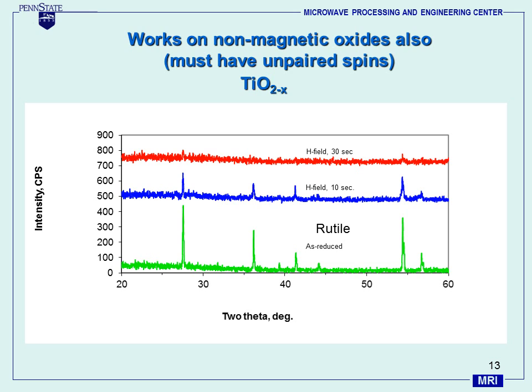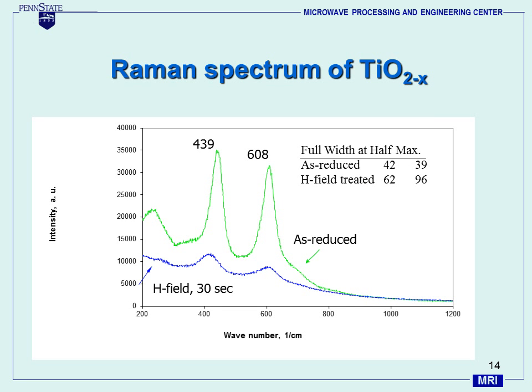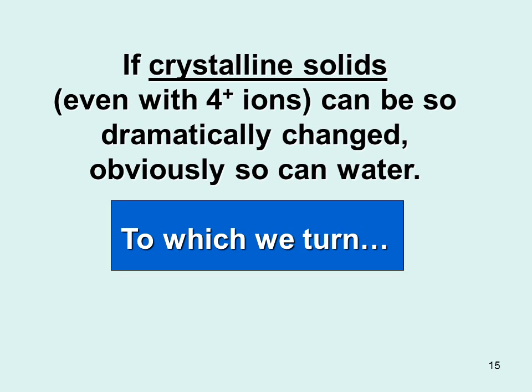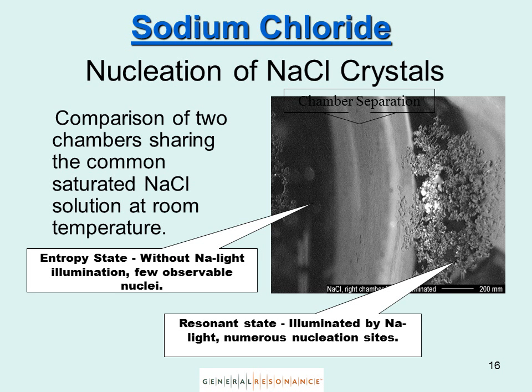Now here I'm just illustrating the difference. Here's titanium oxide, the principal insulator of today's world, and here it is slightly reduced, and in 30 seconds it's gone to amorphous, completely gone. And this shows you we've used all the techniques, TEM, everything else, and here's Raman showing how the titanium goes. Now, what's my conclusion? If crystalline solids with 4+ ions, that means the strongest bonds, think about that, can be so dramatically changed, so can water. So that's the beginning of my lack of skepticism.